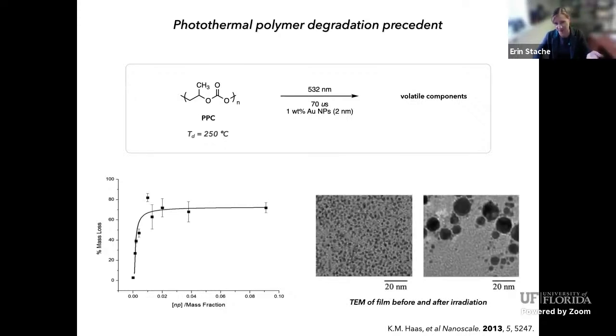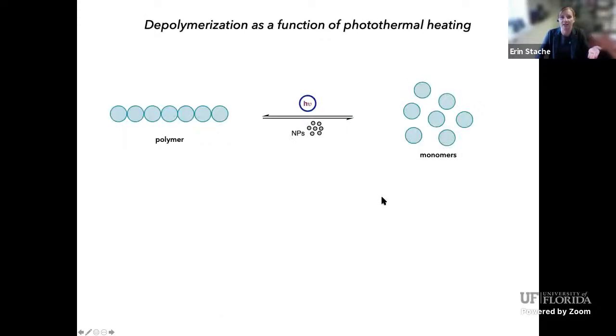Now, the limitation of this approach is, one, it's using gold, which is very, very expensive and probably not the best strategy for degrading commodity polymers. But two, like I said before, gold is not the most stable. It exhibits a very extreme LSPR, but in doing so, it generates really hot temperatures, which can actually melt the surface, and the particles start to aggregate. And once they start aggregating into these larger forms, they lose that surface plasmon resonance, and then they're no longer as effective. And so with this in mind, we thought that we could use photothermal materials to try and degrade commodity polymers, or do depolymerization as a function of this photothermal heating concept.